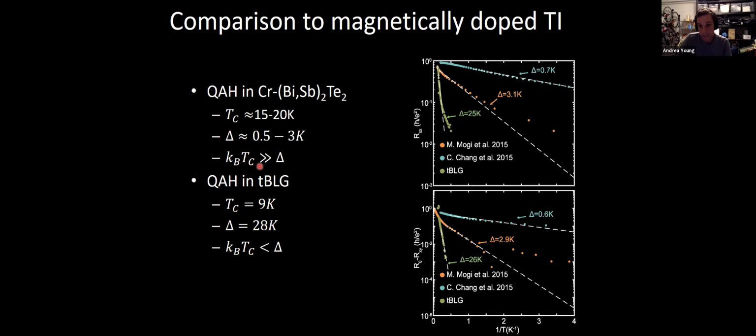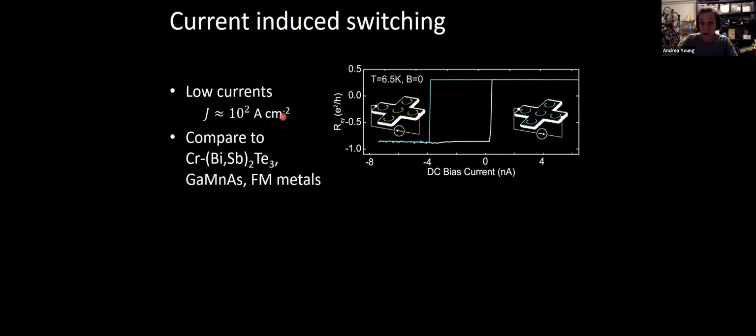And I think really the difference here is disorder. This is an intrinsic effect, we think. It doesn't come from dopants, whereas there you're trying to take a non-magnetic system and make it magnetic by very strong, on the order of 10%, alloying, and it's not even clear that the alloy is really an alloy. It may be interstitials. It's a rather disordered system. So from that practical point of view, this turned out to be nice. You don't need very low temperatures.